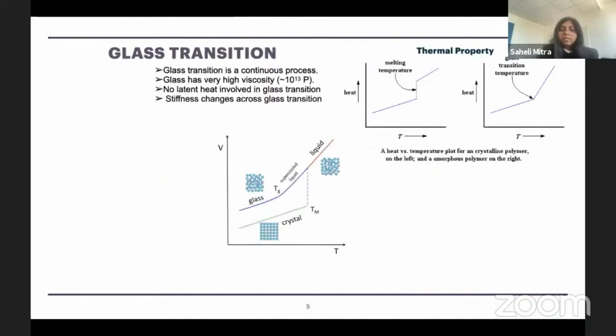Now, as I said, a glass is a disordered, arrested state of matter, but not all disordered states of matter are glasses. A glass is characterized by the glass transition, and the changes that happen during this glass transition. For example, we can think of thermal property. In case of crystallization from liquid to crystal state, there is a well-defined melting temperature where the system releases latent heat and becomes a crystal.